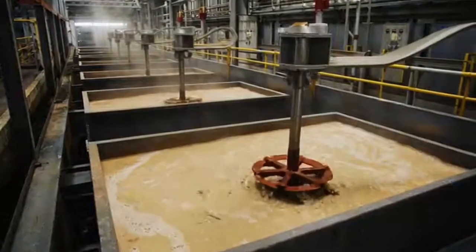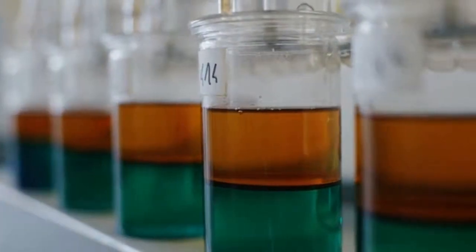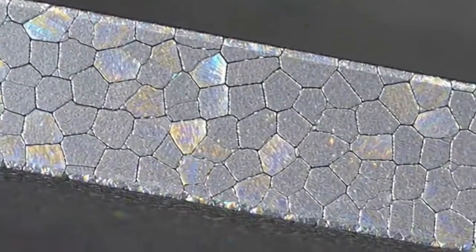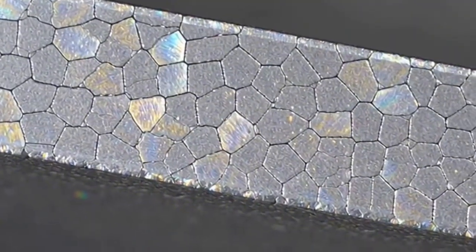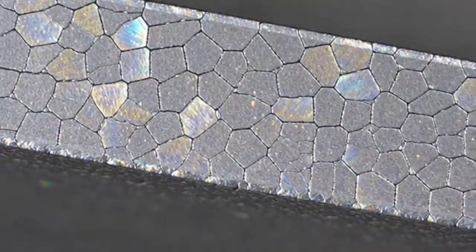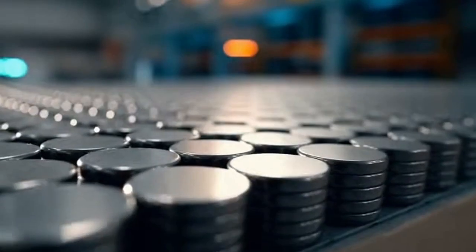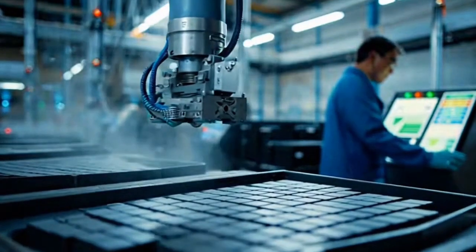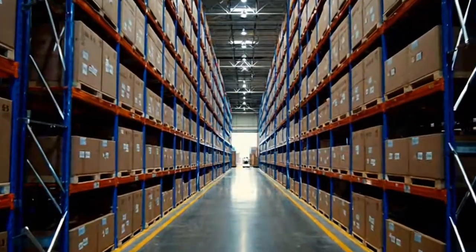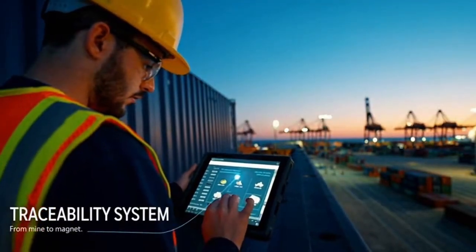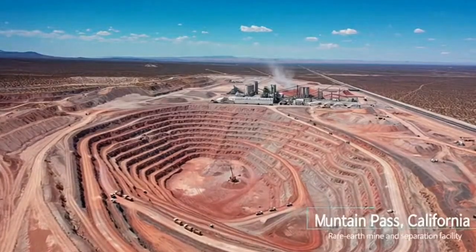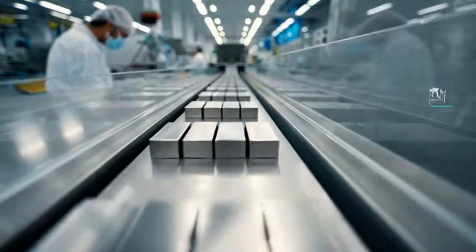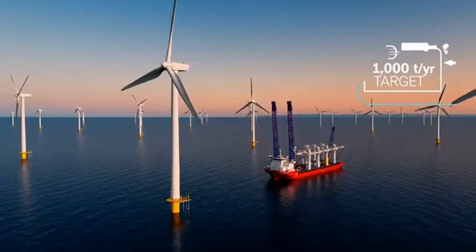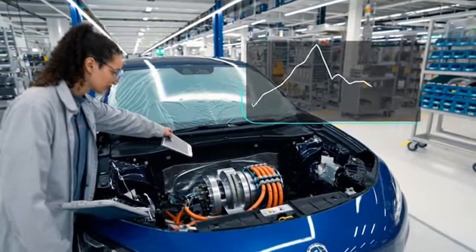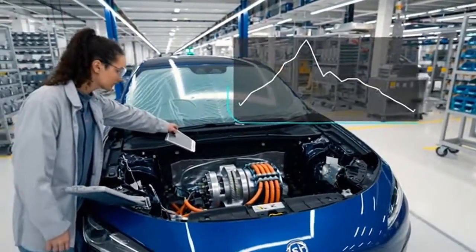Then comes metallurgy: turn that neodymium-praseodymium oxide into metal, or straight into alloy, either by a metallothermic reduction, basically using an even more reactive metal to yank the oxygen away, or by molten salt electrolysis if you need higher purity. Cast the resulting alloy quickly into thin strips to freeze a fine microstructure, use hydrogen to make those strips crack and crumble neatly along their grain boundaries, jet mill the pieces into powders only a few micrometers wide, press that powder in a strong aligning magnetic field, then sinter, heat treat, and apply a protective coating.